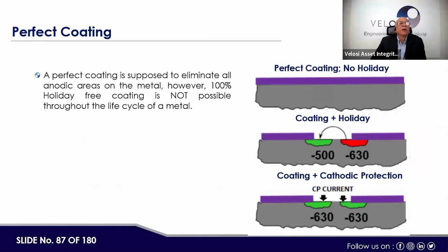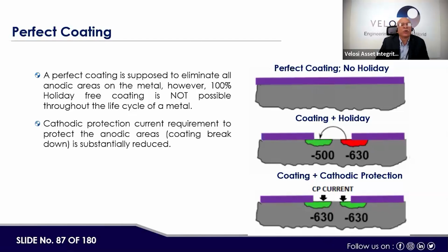So here, a perfect coating means no holiday. If there is a coating holiday, if a break is there, then coating and cathodic protection work together. With a perfect coating, you don't need a CP system. However, if there are holidays or pinholes in the coating system, then we need a CP system. So the CP system and the coating system work hand in hand. Cathodic protection current is required to protect the anode area. Coating breakdown is substantially reduced.